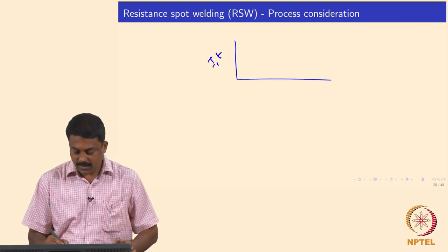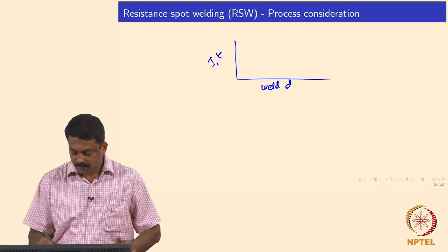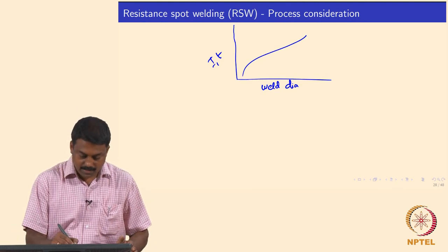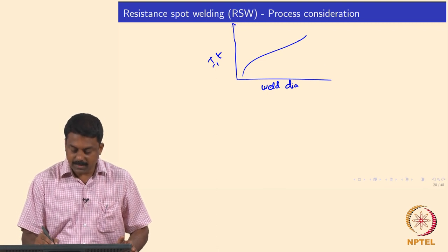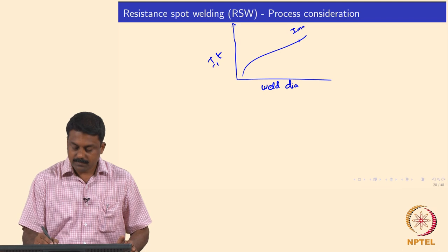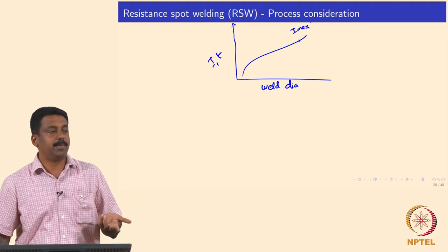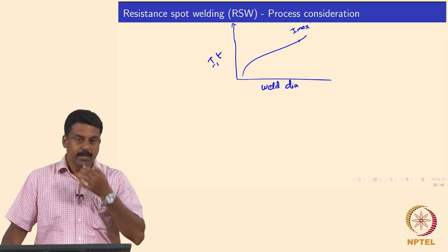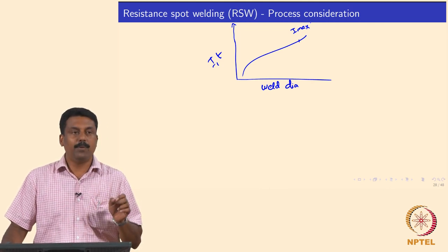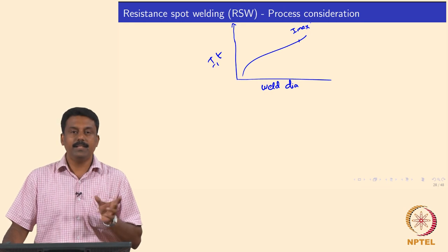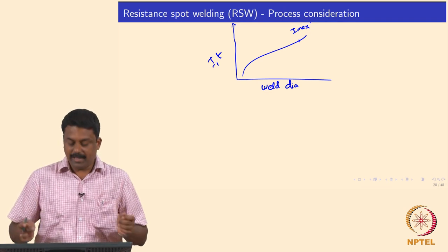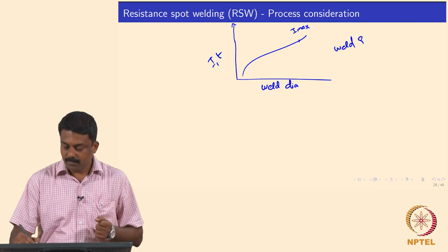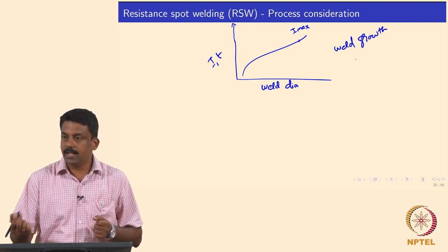We looked at current I_t as a function of weld nugget diameter. Generally the curve follows a typical shape, and we can identify the maximum current for a given time — that is I_max — which determines the expulsion or splashing condition. Automotive industry guidelines generally state the weld nugget diameter should be 4 times the square root of thickness, and from the weld growth curves we can identify the critical current and time needed to achieve that required weld nugget diameter.